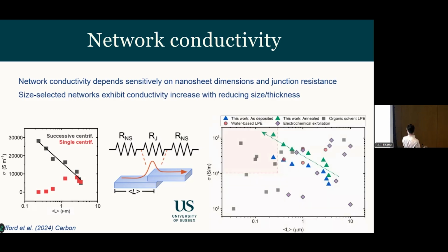Just to put it in some context here, here is a survey of some conductivities for various graphene materials processed in various ways in the literature. You can see, if you take our materials in blue and green out, the general trend is bigger is better. What we're not seeing across these isolated points, rather than systematic studies, is that we're also likely changing the junction resistance, effectively the junction conductivity, and that's what's changing the conductivity trend in our networks.